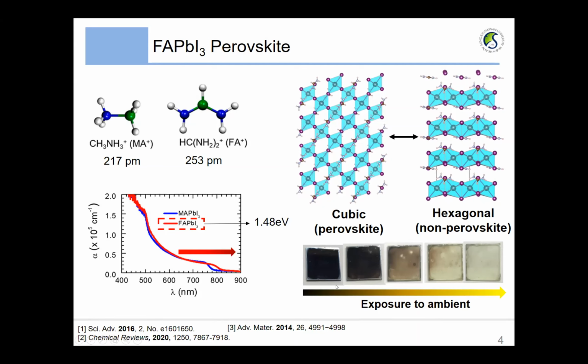However, once the alpha phase forms, it readily converts back to the delta phase because the large FA cation induces lattice strain, which destabilizes the lattice. And then exposure to humidity gradually increases the surface defects, which accelerates this process. So in order to improve the phase stability, additive engineering is highly required.